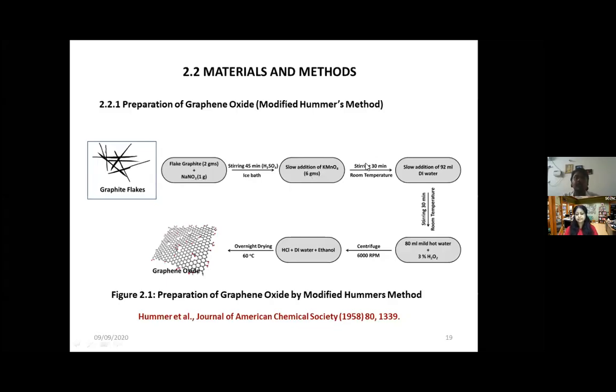Here we obtained a brownish gray slurry, and then we slowly added 92 ml of DI water. Here we observed a brownish slurry and stirred for 30 minutes at room temperature, and then we added 80 ml of mild hot water plus 3% hydrogen peroxide. The solution is transferred to a 50 ml centrifuge tube and centrifuged at 6000 rpm in the presence of HCl, DI water and ethanol.